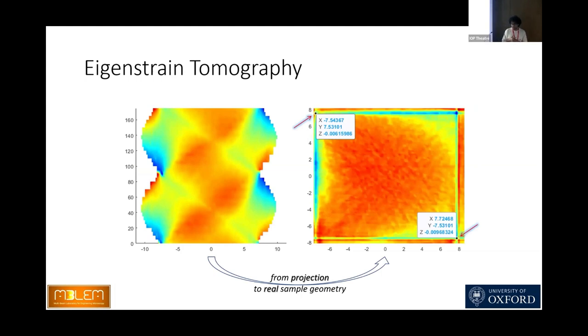Here we see a contour plot of the strain variation with projection number on the left. And you see strain distribution map obtained by strain tomography on the right in one of the scanned planes. We have five layers of strain information.